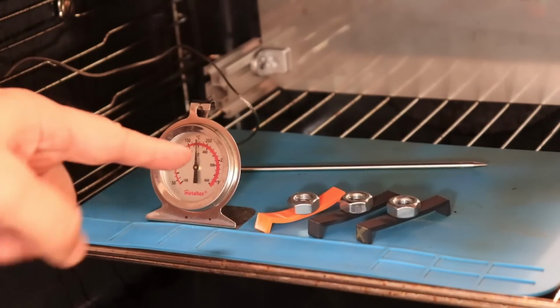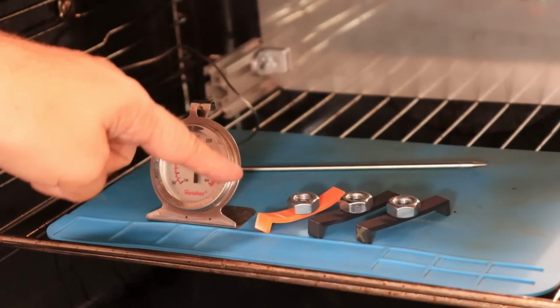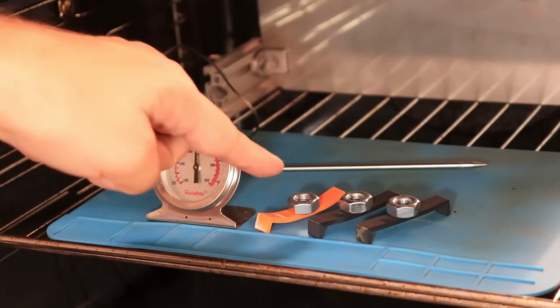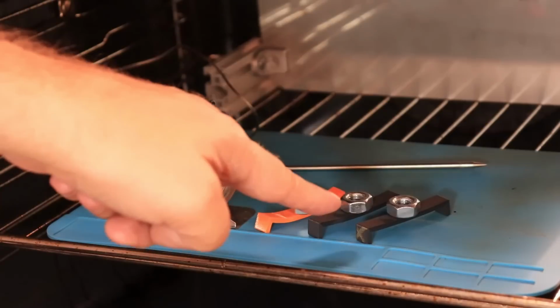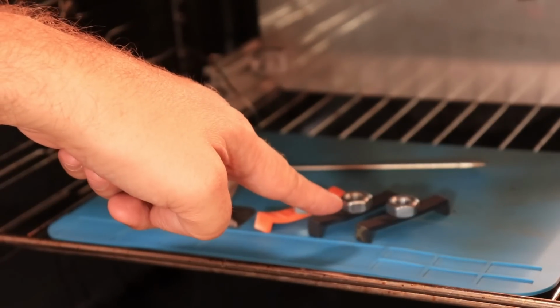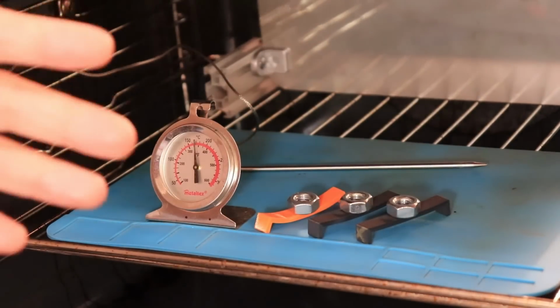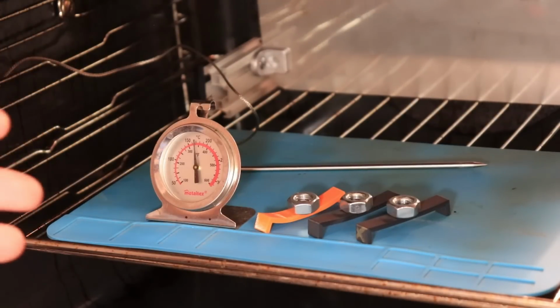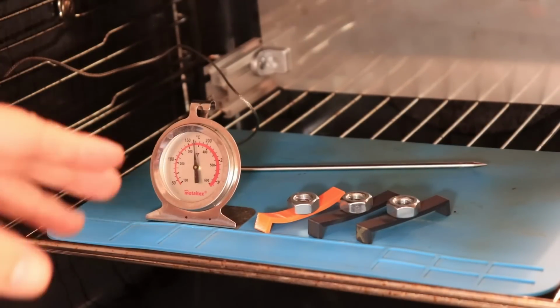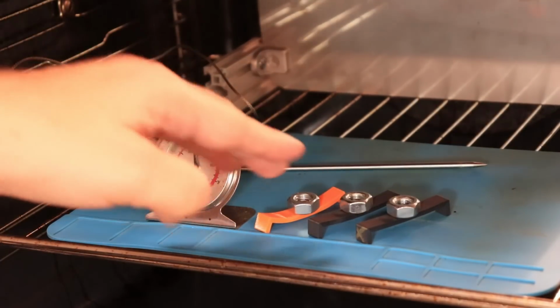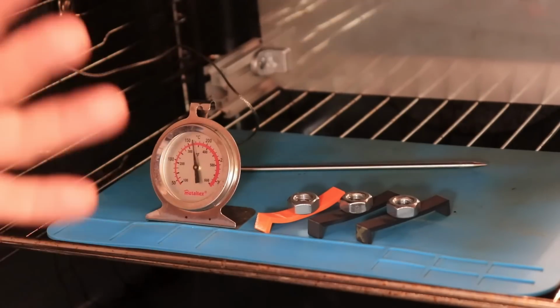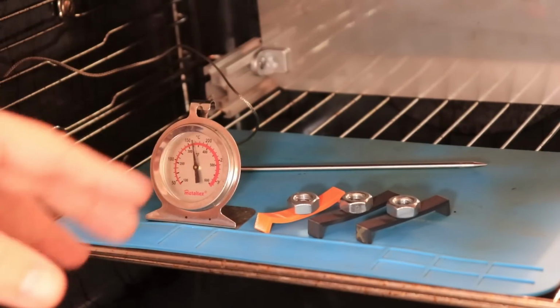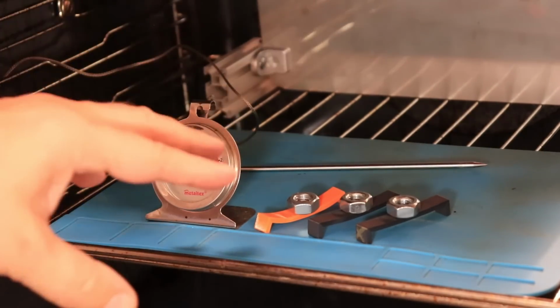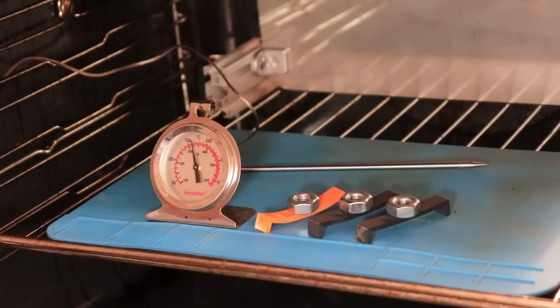And something I expected, I can see now the polycarbonate is completely down, the carbon fiber just a little bit deformed, and just a slight deformation on the annealed version. But it was far above the specifications given on the website. But don't forget, this is not standard testing. This load is a little bit lower than the standard ISO 75. But this is my regular testing, which I always do with these materials.